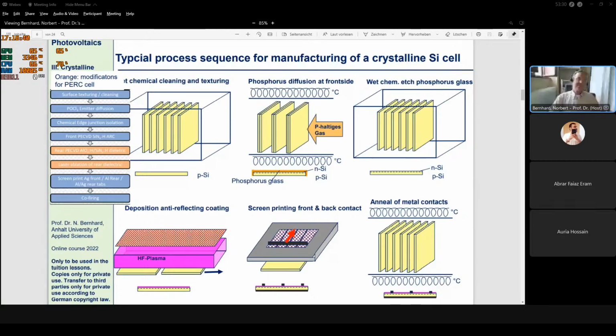Okay, you see here on the left-hand side, the blue boxes, it's in principle, again, what I just explained. The two orange boxes, this is a modification which has to be made for the new PERC cell, because you might have noticed the process flow which I have described now is just the old aluminum back surface field cell. For the new one, for the PERC cell, we not only need a passivation layer on the front side, we also need a passivation layer on the back side.